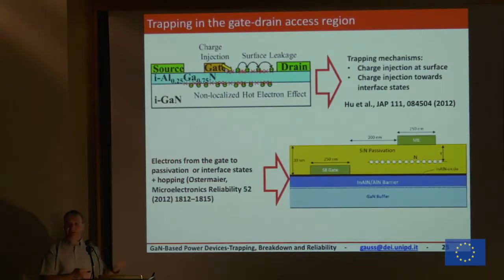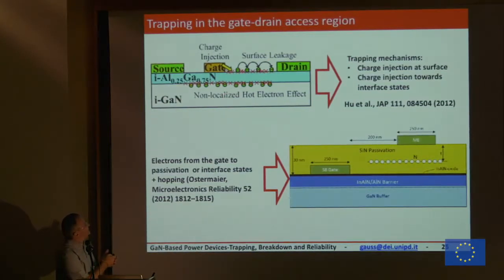Moreover, we may have other trapping conditions, not only under the gate, but we have a very high field from gate to drain. Whenever we are in the off state, negative gate bias, high VDS, we have an extremely high electric field. And this induces injection of electrons that may go through the surface, that may get injected in the different areas here. So we may have trapping or any charge storage in any area of the device active area. And this is our point.